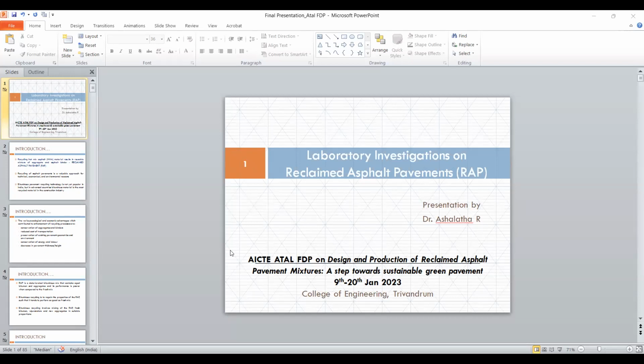So now the question you would really want to know is, already adding the RAP is going to create some issue in the fatigue. Why would we want to really add an additive like Sasobit? Now there are a few answers to this. Whatever laboratory work that we do on the warm mix additive seems to be counterintuitive when these things are checked in the field investigation. What happens is these warm mix additives actually give enhanced aggregate packing in the field.